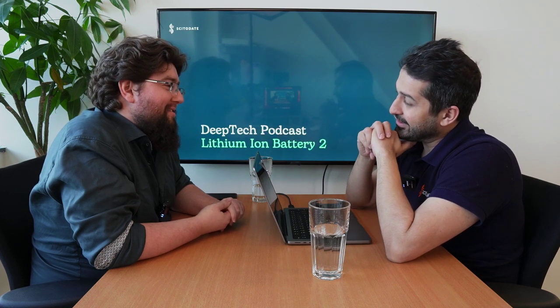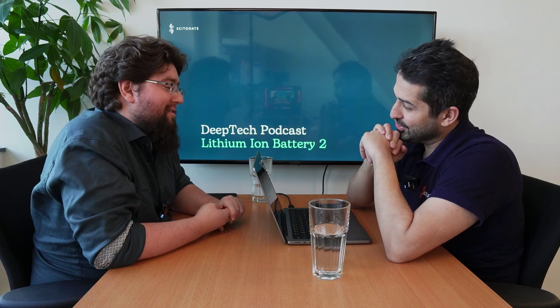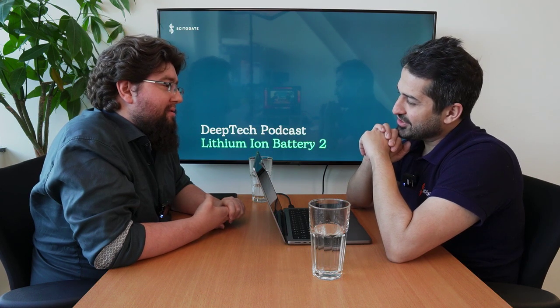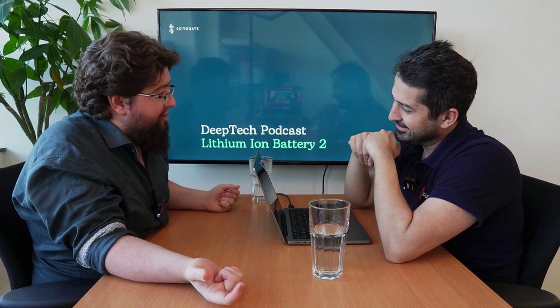You see that it bulges. So if you are in a high state of charge, when it's fully charged, if you're removing cobalt, the oxygen becomes a gas. So when it's fully charged, the cathode is empty. So then there's no more lithium left. So you start taking cobalt out. There's extra oxygen, which goes up. So do they get released? Do they get mixed into the electrolyte? That happens.